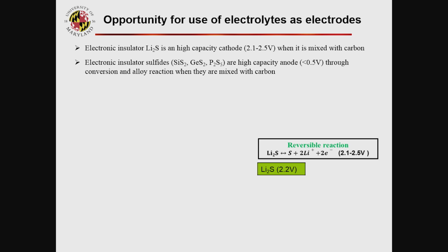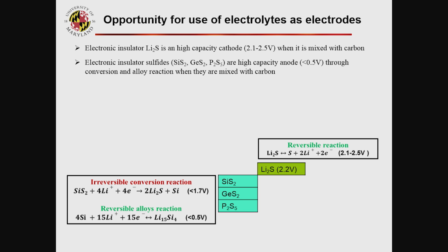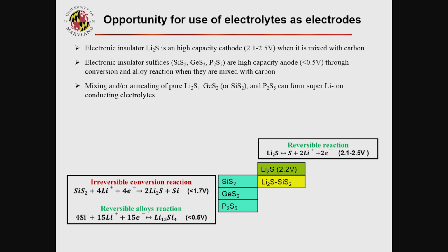And also, a lot of metal sulfides are anodes, through the conversion reaction. So if lithium sulfide and metal sulfide are mixed together, one can function as a cathode, one can function as an anode. So they already know this is a really very good anode. Fortunately, if you mix these two together, it's a well-known electrolyte. So this is not a single case. If we mix these two together, this is also a well-known cathode.